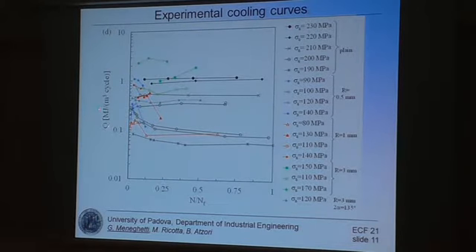Now, if you plot the dissipated thermal energy in a unit volume of material per cycle, you can see that the thermal dissipation is quite constant in the case of plain material, but if you look at a very sharp notch, the blue points, you can see that the dissipation has a typical value at the beginning of the test, and then it tends to be very low as soon as the crack starts from the notch tip. So the material cools down at the notch tip because the crack propagates farther from the notch tip. So you obtain typical curves like this.